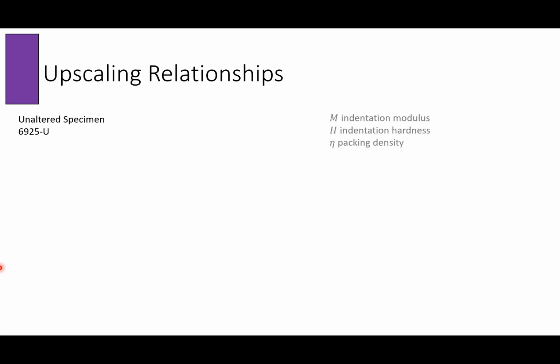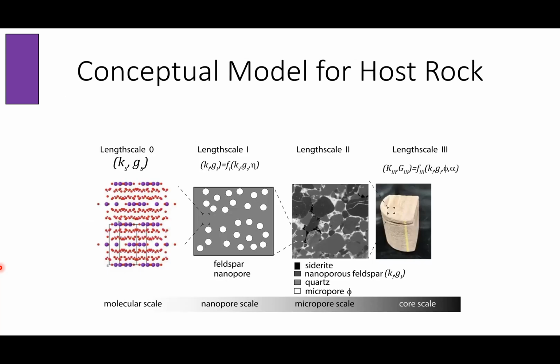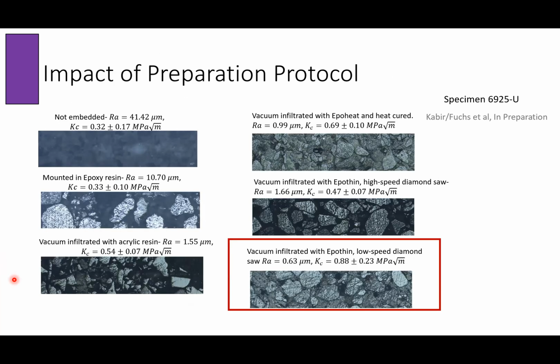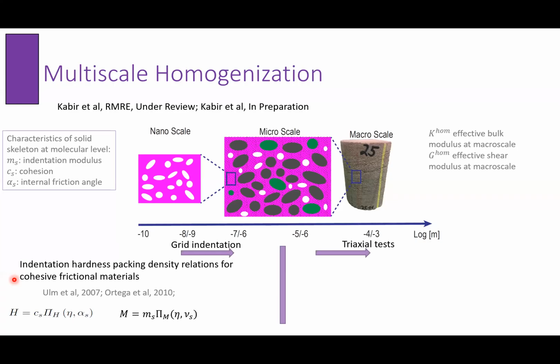Okay, so for the plastic property, we're looking at the cohesion. I'm trying to see where I show it. Okay, so if you look over here, from the indentation, I have the modulus and the indentation hardness. And by applying backward micromechanics, I can link it to the cohesion of the skeleton here and the friction coefficient in this case. So I can extract it.